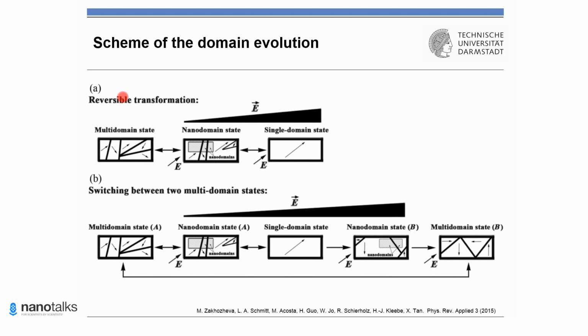However, if you increase the field after that, again this multiple domain contrast will appear, and after that we already will have only switching between two different multiple domain states, basically A and B.